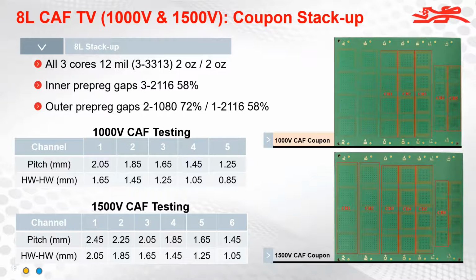And because of the capability to wet that glass to resin bond, that is the common location of failure. And so for this type of material, these types of applications, really the primary issue is Z-axis, and then secondary is the whole wall to whole wall. And this 1,500 volt CAF test shows some very excellent capability on these types of test vehicles. Yeah, high adhesion combined with fracture toughness, those together would lend itself very well to a CAF resistant material. Correct.